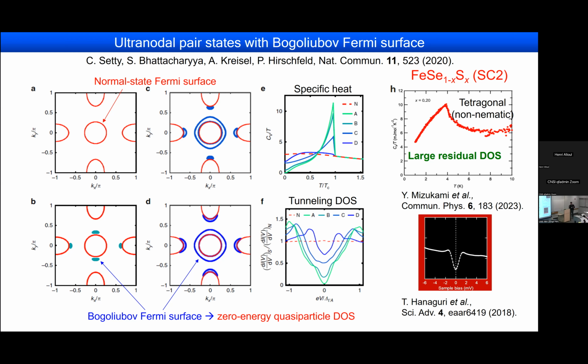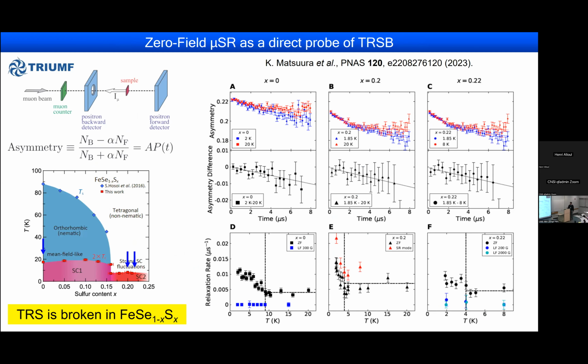Okay, so the next question I would like to address is whether the time reversal symmetry is broken or not in this material. So we have performed the zero field μSR measurements, which is a very sensitive probe of the internal magnetic field inside the sample, and so can be used as a direct probe of the time reversal symmetry breaking. So we have measured 3 samples. One is iron selenium inside the nematic phase, and these 2 are outside the nematic phase. In all cases, we see that the μSR relaxation rate is enhanced below Tc, which is an indication that we have some kind of magnetic field appearing inside the sample below Tc. So this is evidence for the broken time reversal symmetry in these samples, both in SC1 and SC2.